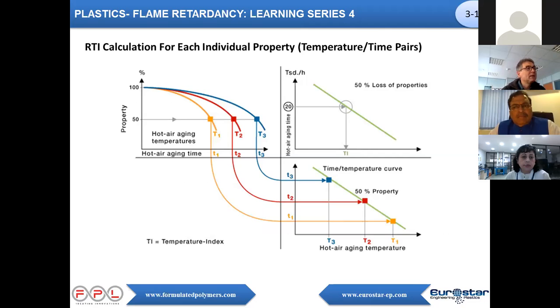So just to explain, we are measuring, for example, the properties versus time. The yellow curve is, for example, let's imagine it has 200 degrees C in an oven. You will see a property. It can be an impact property, a tensile property, and of course, during time, the material is aging and the property is going down. An important point is what they call the half-lifetime period, meaning that the property is cut into two, a retention of 50%.